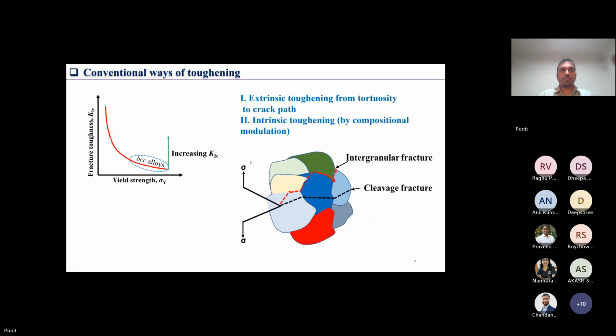when we want to design newer materials with higher strength and higher fracture resistance. So in the case of BCC materials, what we want to do is increase their fracture resistance without affecting the yield strength. And usually there are two ways we can achieve this in BCC materials. We can have extrinsic toughening from tortuosity of the crack path. Usually what I mean by that is, BCC materials usually fracture by cleavage fracture or intergranular fracture. And if you have a crack path which is tilted or twisted, in that case you can have a higher fracture resistance in this material.